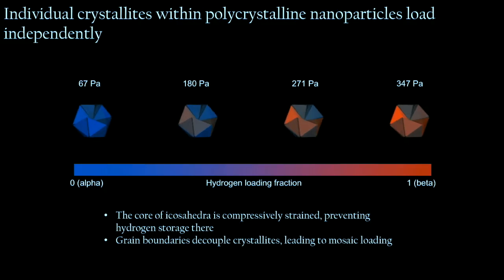But when we reconstruct three-dimensional images of what the icosahedral nanoparticle is doing, you can see that there are different crystallites making up this nanoparticle, essentially kind of prisms, 20 tetrahedra that make up the icosahedral nanoparticle. And in equilibrium, each of those tetrahedra is transforming or is changing phase at a different pressure. This is something that I call mosaic loading, and it essentially gives rise to a reduced energy storage or hydrogen storage capacity for these polycrystalline nanoparticles.